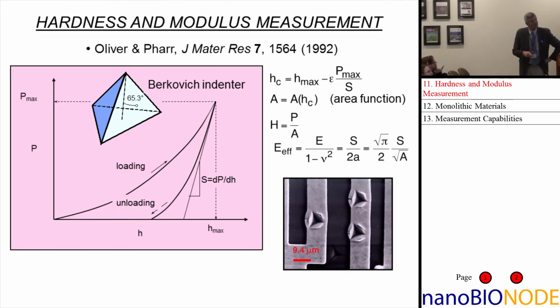So the question that was asked is, how do we get these two things separately? And that requires a slight leap of faith, and a lot of people don't appreciate this, but there is a slight leap of faith. It is based on the idea that the Sneddon model is correct, but the Sneddon model is based only on elastic deformation. The plasticity is not built in there, and there are complications that are as a result of that. But if you believe the Sneddon model, then the basic way that you get those parameters is through this series